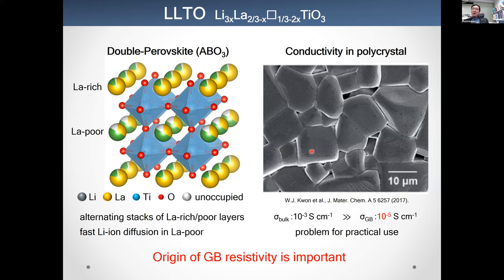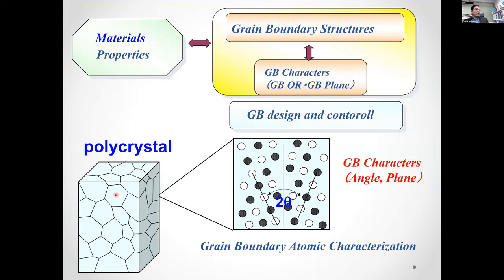And from the Cole-Cole plots, it has been reported that the conductivity in the bulk is much larger than the grain boundary conductivity. Therefore, it is important to understand the origin of grain boundary resistivity. In the case of polycrystalline materials, the grain boundaries have very different grain boundary characters. Their properties and structures depend on the grain boundary character. This is very important. Grain boundary character means the misorientation angle between two adjacent crystals and also the grain boundary plane.